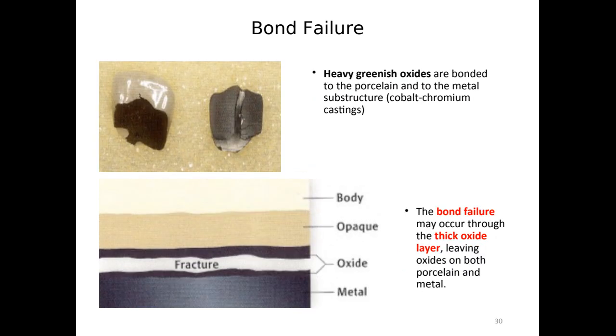Heavy greenish oxide is bonded to the porcelain and to the metal substructure, and this is mostly for the base alloy, cobalt chromium casting. The bond failure may occur due to a thick oxide layer, leaving oxides on both the porcelain and metal. So if the oxide layer is too thick, it may break, and when they separate from each other, we're going to see a layer of oxide on the porcelain and a layer of oxide on the coping.